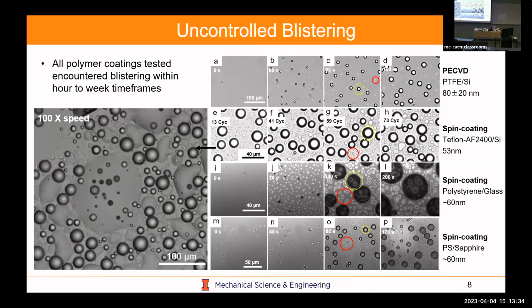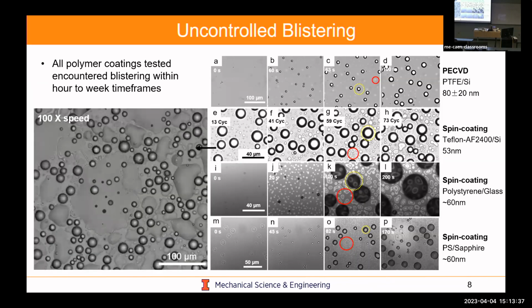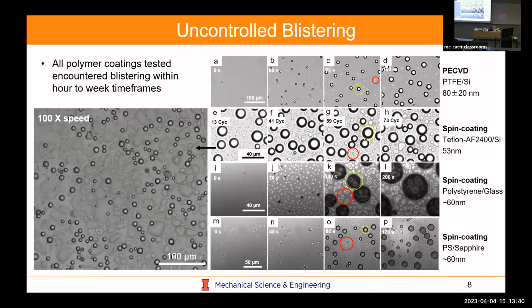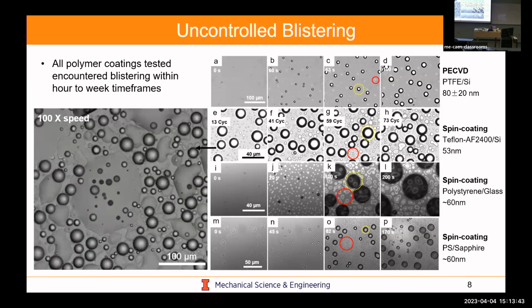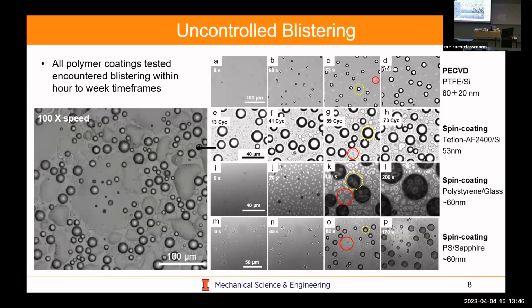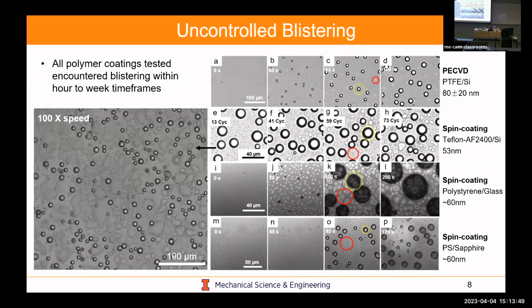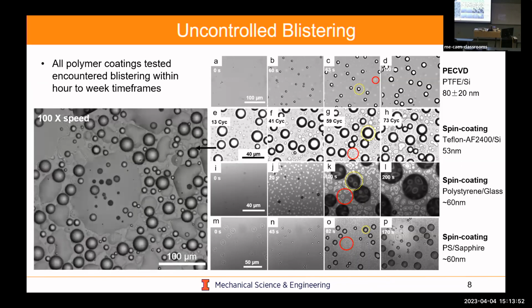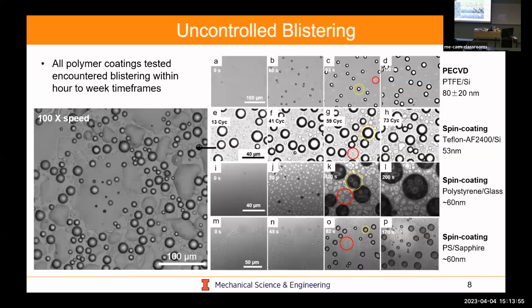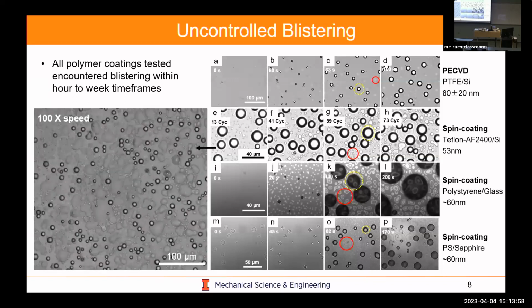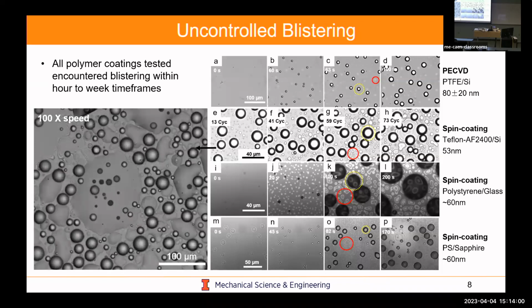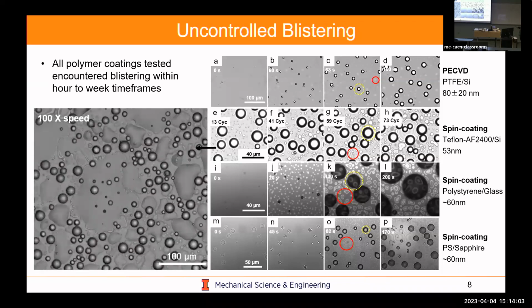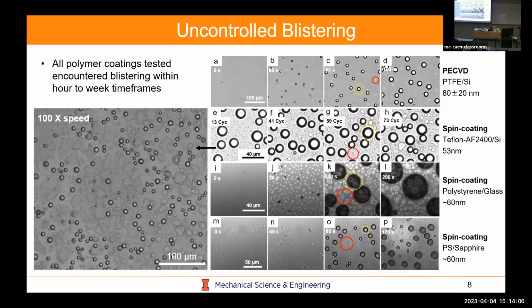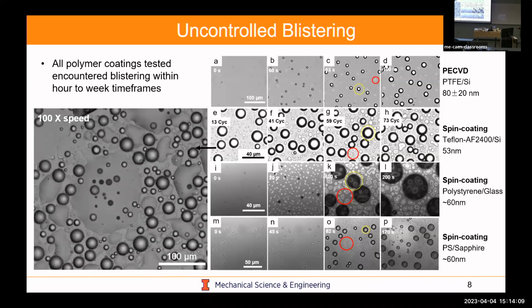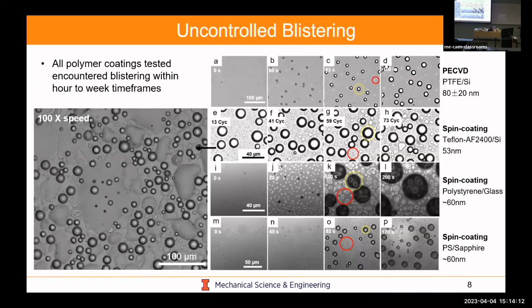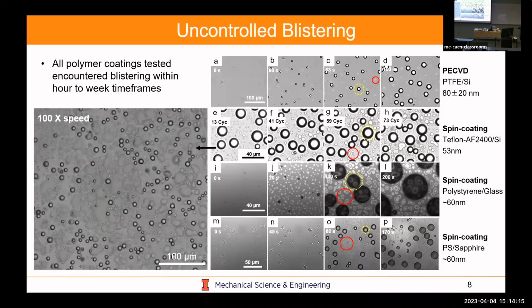And so we first started out looking at many different surface coating combinations. Typically what you'll see when you condense, this is an optical microscopy video. These are water droplets condensing from the atmosphere on a polymer coated silicon wafer. You'll see these blisters form, and this has been known for 30 or 40 years now. These blisters will form, they'll coalesce, grow, and then eventually you'll actually de-wet and the entire coating itself will fall off the surface. So what we noticed was, whether we do PECVD, like a PTFE Teflon-like coating on silicon, or spin coating, things like polystyrene, Teflon AF formulation, we see the presence of these blisters over time.